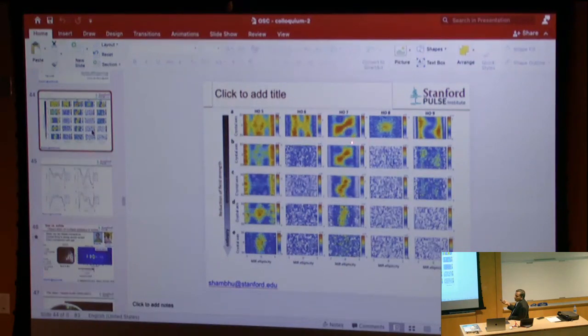So maybe I will leave it at that, and maybe we can discuss more later, I guess maybe tomorrow. This could lead to really interesting chiral strong field physics, especially in Weyl semimetals, where the material is actually chiral throughout the whole 3D bulk. So there you clearly see the chiral response. Here only the surface is chiral, not the bulk, right? And also there is an unavoidable coupling between the surface and bulk. That makes the fully circular case a little bit complicated to declare anything. But at medium ellipticities, there is a pretty clear chiral response you see everywhere.